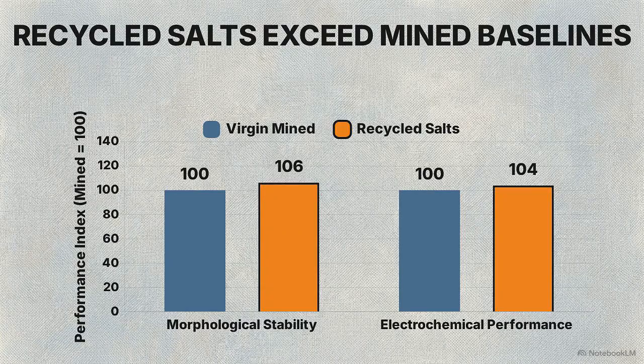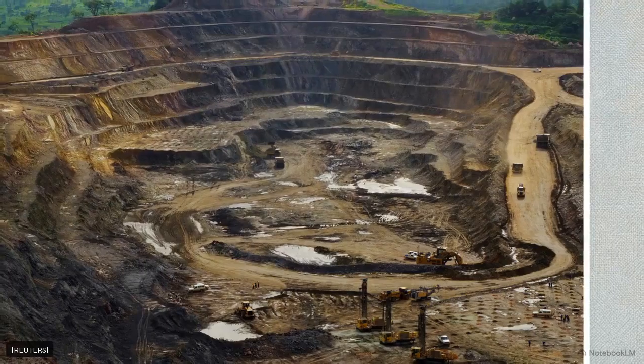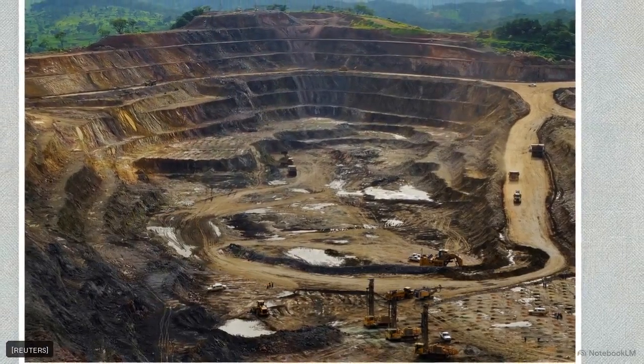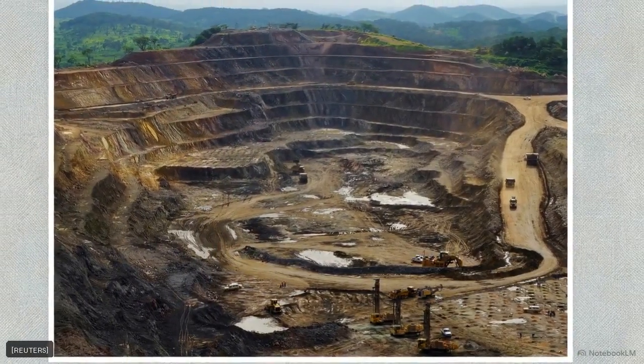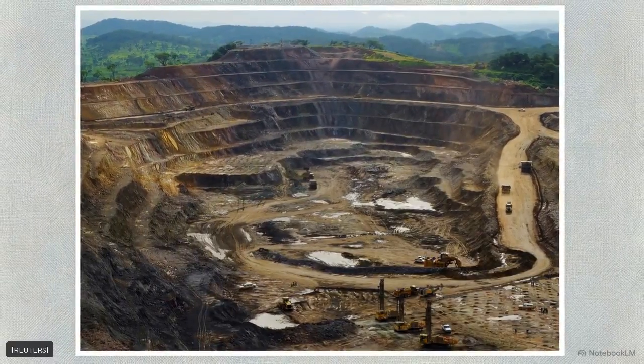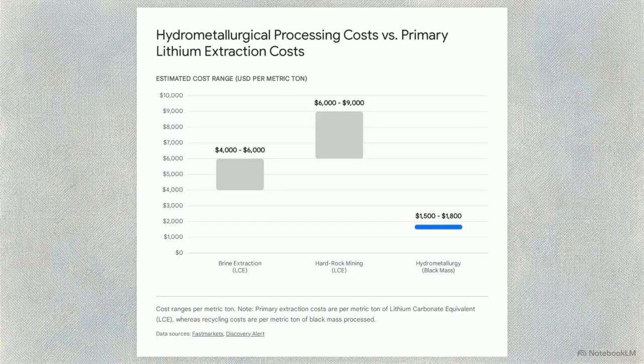Empirical testing consistently demonstrates that these recycled metal salts match and often exceed the morphological stability and electrochemical performance of virgin mined materials. The true advantage of this process reveals itself in the economics. We can directly evaluate the all-in processing costs of hydrometallurgy against the immense expenditures required for primary hard rock mining and brine evaporation. This chart compares processing costs per metric ton. There is a stark contrast between the hydrometallurgical recovery of black mass, which costs between $1,500 and $1,800, and the massive $6,000 to $9,000 cost floor of hard rock lithium mining.